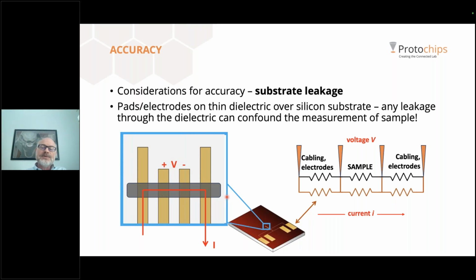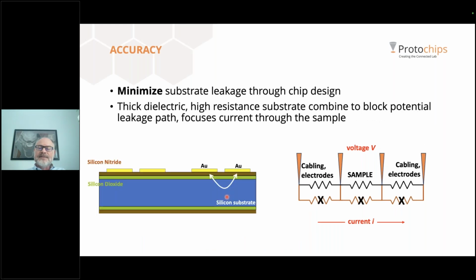So one of the potential sources of leakage is through the chip substrate. The substrate is relatively thick, 300 microns, and the pads see the same bias as the sample because they're part of the circuit. Now, fortunately, this is something that the chip designer and supplier can address. All of our electrical chips are made using a special substrate with 2 features: very thick silicon dioxide films under the silicon nitride top layer and a high resistivity silicon substrate.